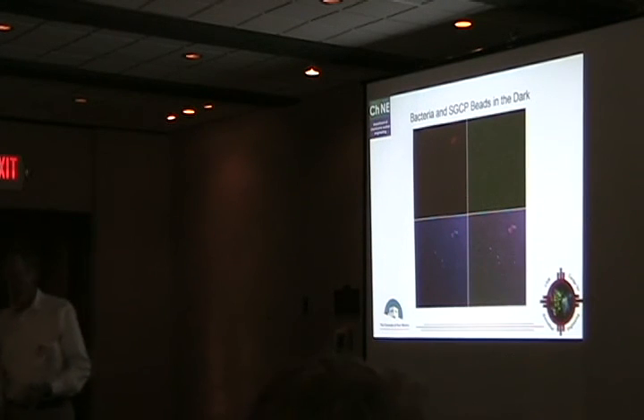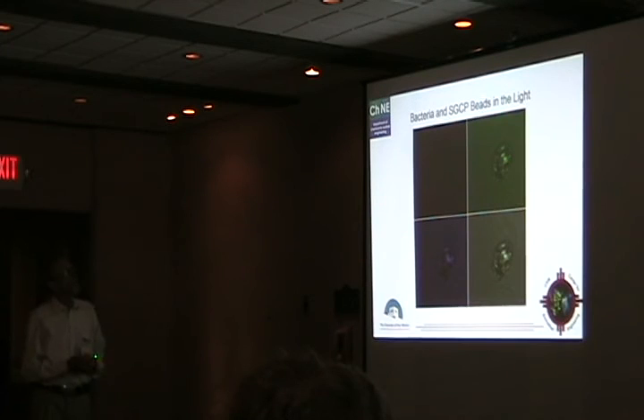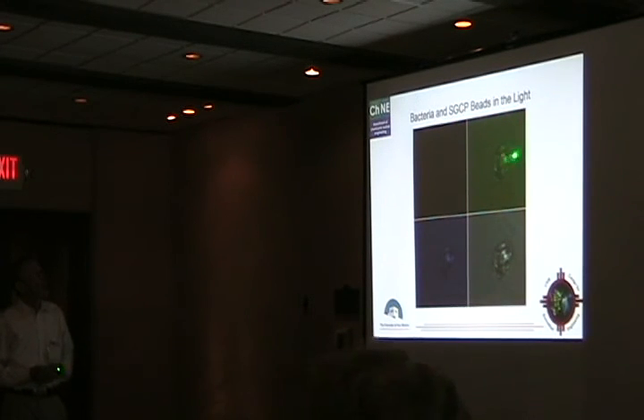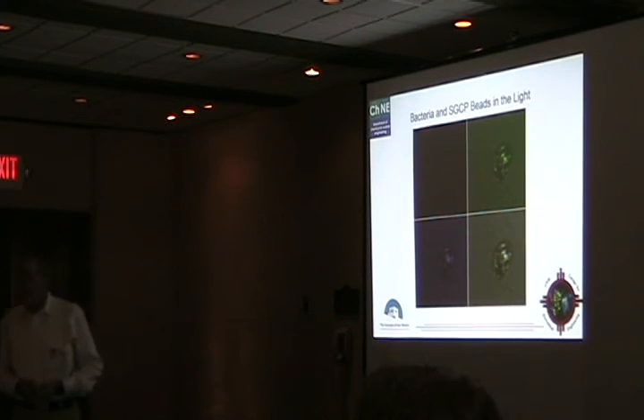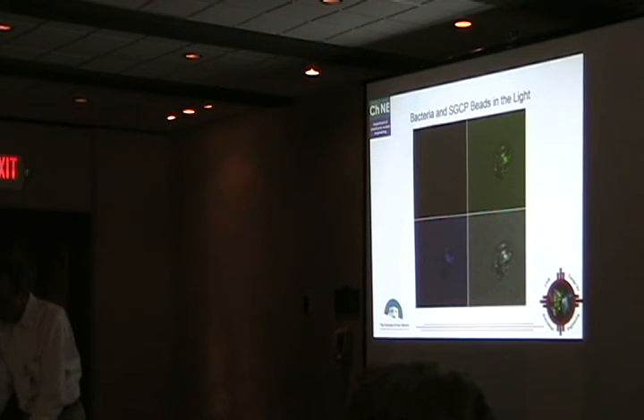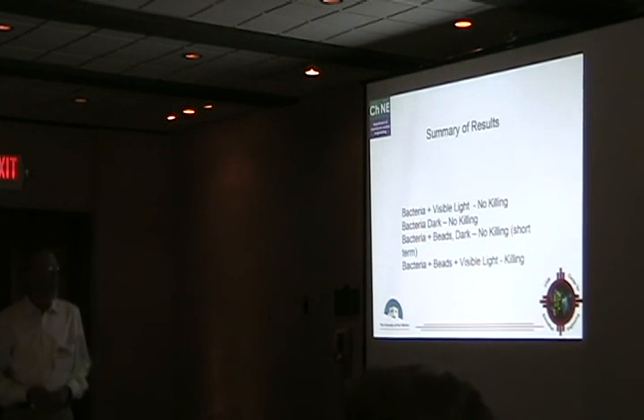So just attaching the bacteria to the beads doesn't kill them. On the other hand, if we irradiate them with visible light for about 30 minutes, you can see the green, the signal for dead bacteria, as well as the red, so you get both red and green, and you can see the composite. I don't believe any of these bacteria on the bead are viable after a short amount of radiation. So we think that these surface-grafted conjugated polymers can be very useful for biocidal activity.